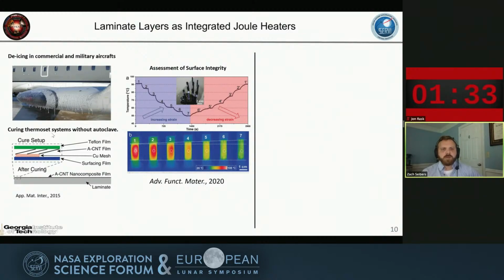You can use these conductive joule heaters as a means of setting up thermosetting materials, which could also be incidentally used in repair schemes on the lunar operations or in space. You have a viscous thermoset epoxy, apply current to the material, heat it, and it would fuse any damaged areas. And then finally, you can use this as an indicator that damage is occurring in the surface. And there's a big field that's really popping right now with examples of various groups looking at joule heating performance as a function of material strain or an inherent damage to the surface from a variety of sources.